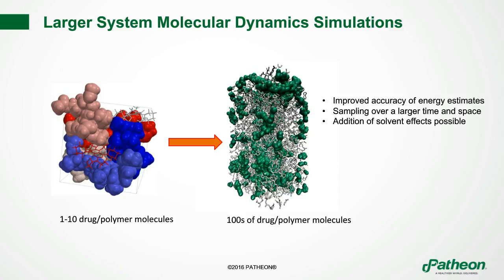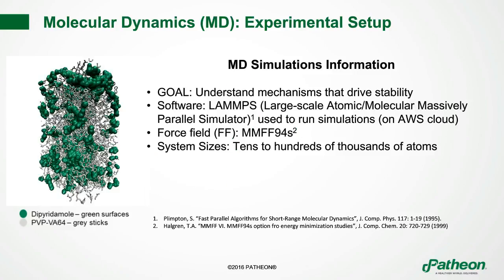And we run these on a high-performance platform using Amazon Web Services Cloud, which you'll see here on the next slide. So the actual setup that we run is using a software system called LAMMPS, which is freeware. It was developed at the Sandia National Labs down in New Mexico. The force field that we use is the Merck molecular force field, the static version, and the system sizes, as I said, are anywhere between tens to hundreds of thousands of atoms. Now, we run these simulations using high-performance computing platform Linux systems on AWS Cloud. And so essentially we're renting CPU time from the AWS Cloud. And that allows us to cut down on costs because we don't have to have our own internal hardware. So if you look at the image on the left, you've got dipyridamole, which is the drug that Tom was talking about, in the green surfaces, and PVPVA64, polyvinyl pyrrolidone vinyl acetate, are the gray sticks.